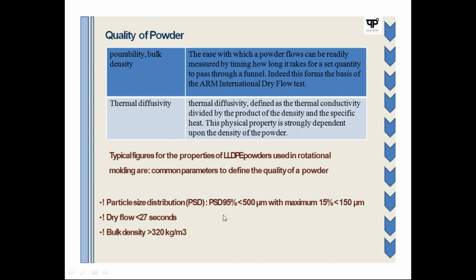Now the particle size distribution: 95% should be less than 500 microns, and a maximum of 15% is less than 150 microns. So that particular part you can use according to your requirement.